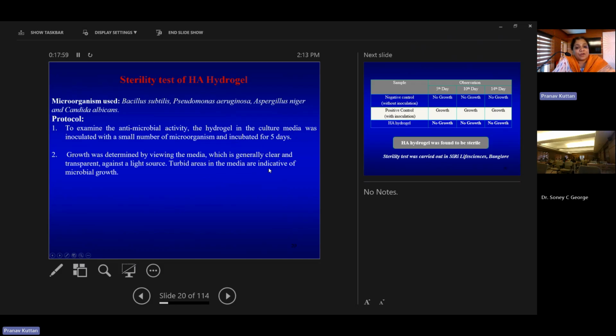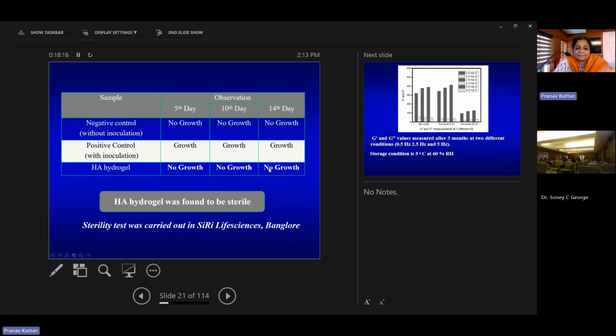Then for a product to be used, it is very important that sterility test should be passed. So different microorganisms were tested, like Bacillus subtilis, Pseudomonas, Aspergillus niger, etc. As per the standard ISO protocol, sterility test was done, and we found that there was no growth found in the hydrogel. So this was found to be sterile.